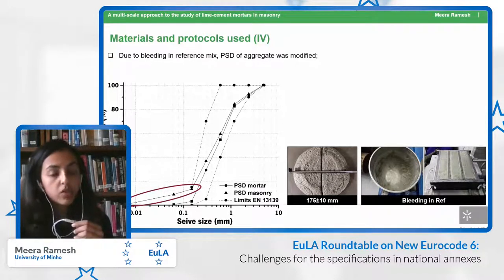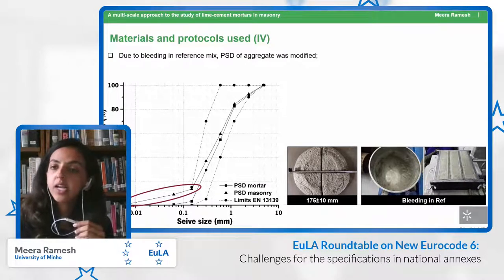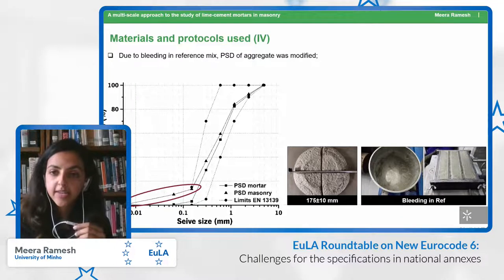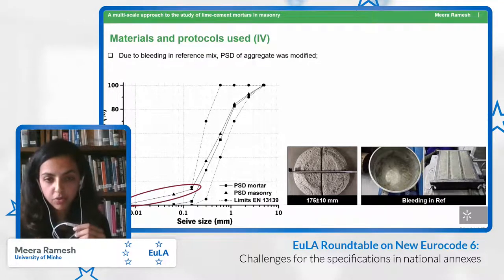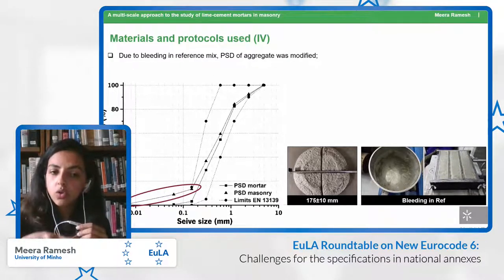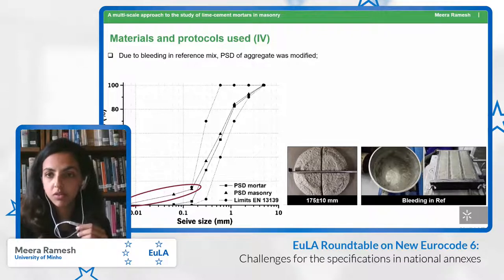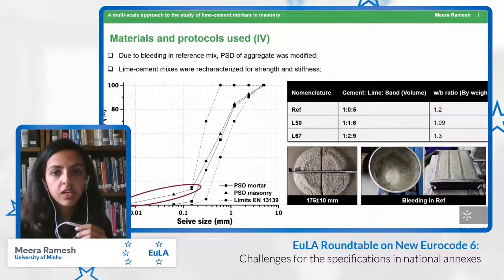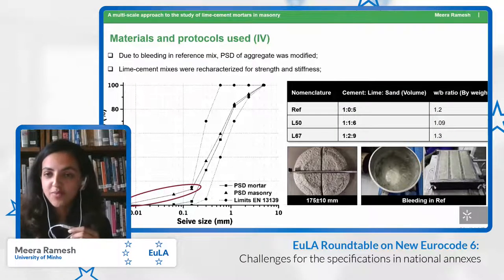So what we did was we introduced a filler, a silica-based filler in our aggregate, which had a particle size ranging from 0 to 63 microns. And that is why you see two particle size distributions on the screen right now. This seemed to solve our problem, but by this time we had already completed the mortar level study.